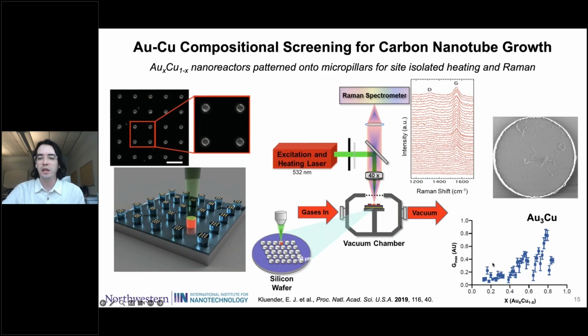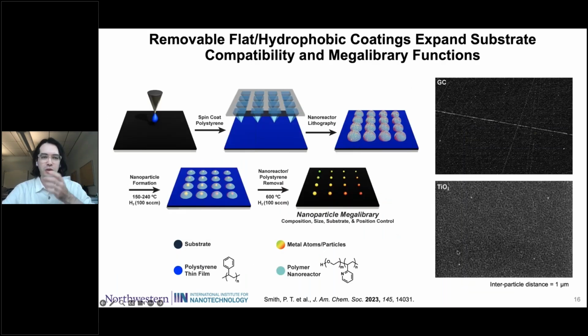And so then we can screen across the gold copper design space and discover that a gold 3 copper composition has the highest activity for growing single-walled carbon nanotubes. And it's a composition that had not been discovered previously. And so now we're getting towards increasing the complexity of megalibraries even further.